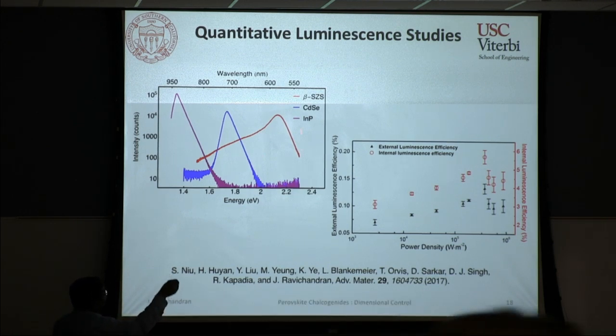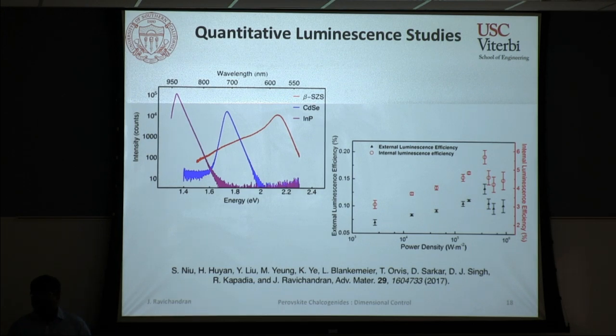If we quantify what is the luminescence efficiency of this system, we found that the luminescence efficiency was a fraction of a percent in external luminescence efficiency, and the internal luminescence efficiency was a few percent after we correct for absorption and reflection losses.